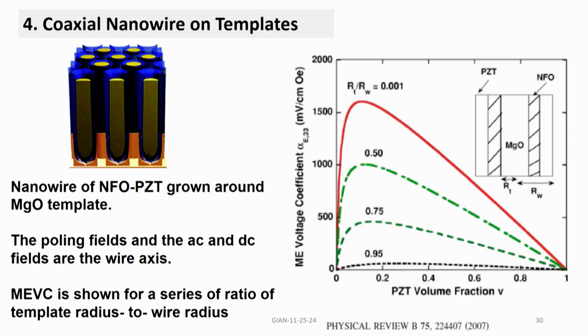And this one is coaxial nanowire on a template. Here the template is magnesium oxide, that is this cylindrical substrate, and nickel ferrite and PZT, they are grown sequentially on the substrate. So, you have nickel ferrite layer, then you coat it with PZT. So, it is a coaxial nanowire on a template.